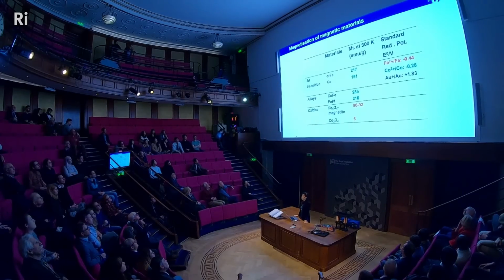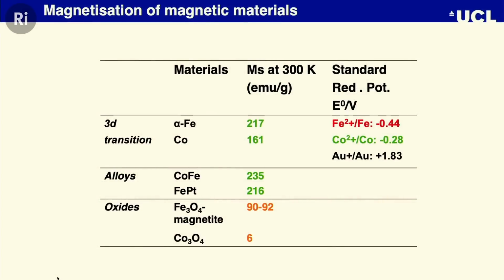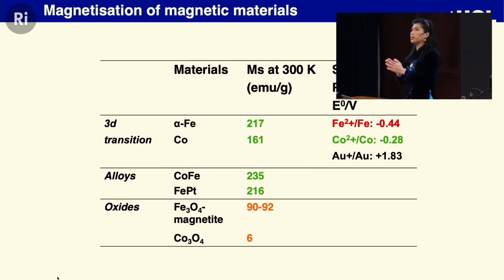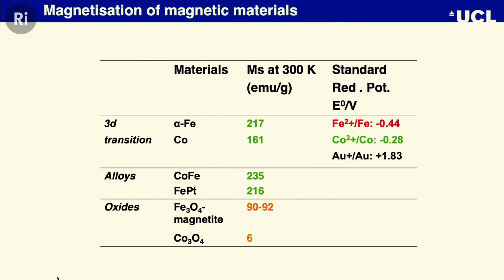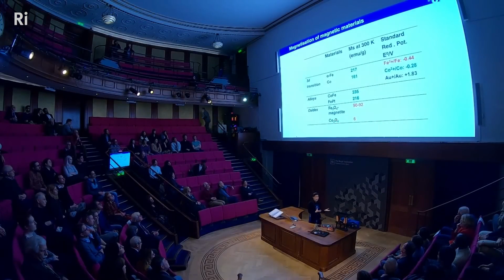Now, we need a particle with good saturation magnetization. What does it mean? When you introduce a field to the particles, like in a ferrofluid, they become magnetized, and with the increase of field, the magnetization goes up and up and up, and at some point it plateaus. That point is called saturation magnetization. With the saturation magnetization of different materials, you can compare that student A can make better than student B, or lab A better than lab B, because you can standardize this saturation magnetization and compare them.